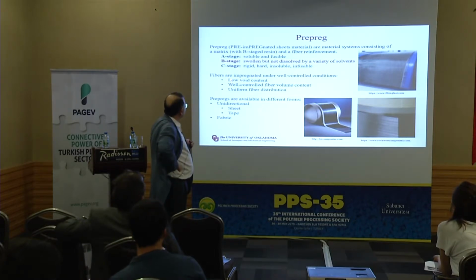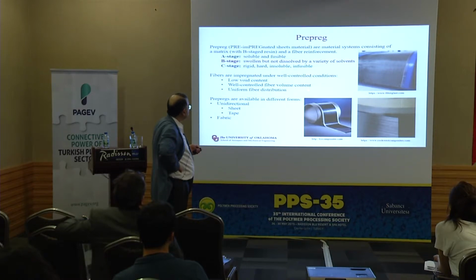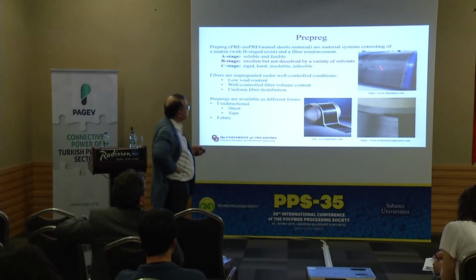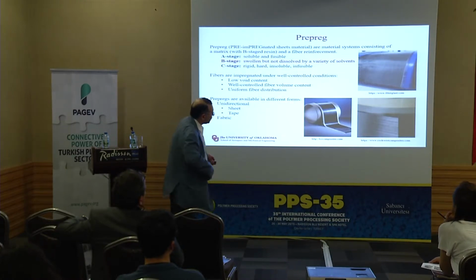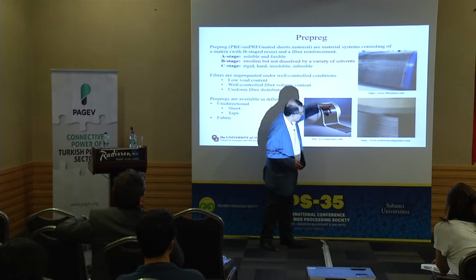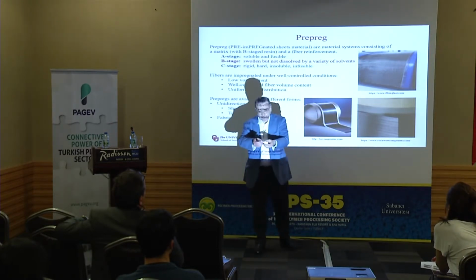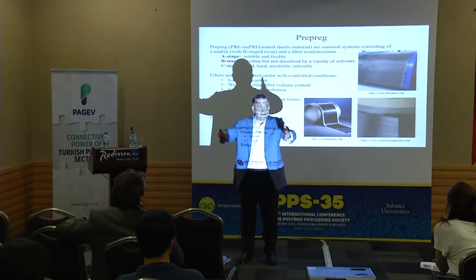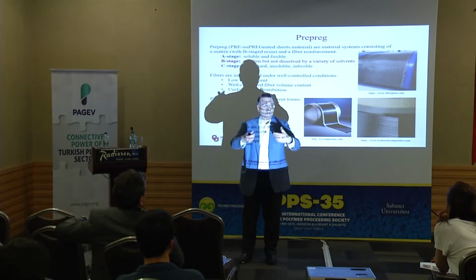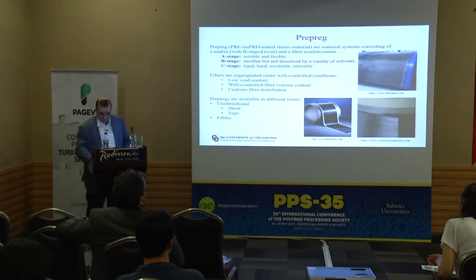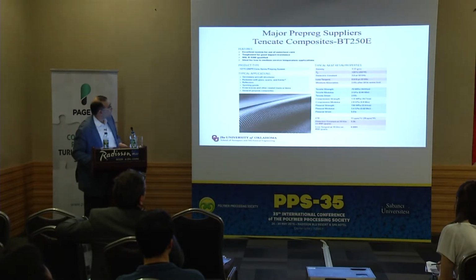Okay? Now, the prepreg is supposed to be good quality, so you will not have voids. You have a very nice uniform fiber volume content, uniform fiber distribution. You can get it as a unidirectional sheet and tape or fabric. These days, fabric is much more common, but you can get unidirectional. But you have to be careful in handling these unidirectional tapes. These are carbon fibers like this. All fibers are in this direction. You get your tape, you cut it, you hold it, you peel it, but it is very easy for this to separate. Okay? There's not a whole lot holding these fibers in this direction. So if you bend it or don't handle it right, it is also a problem during layup. I personally don't like working with unidirectional in the lab. We mostly use woven fabric.